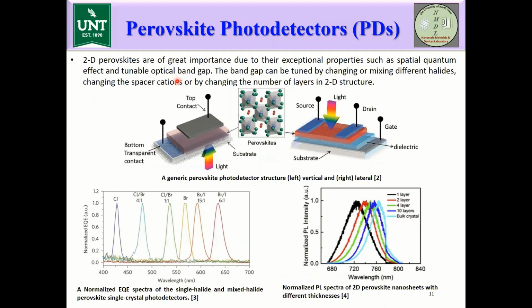Now, the band gap of these perovskite materials can be changed by changing the halide concentration. As you can see here in this figure, the PL peaks shift with changing the halide concentration or changing the halide completely. Or we can change the number of two-dimensional material layers. Here you can see the different layers of 2D perovskite material have different PL peak positions.